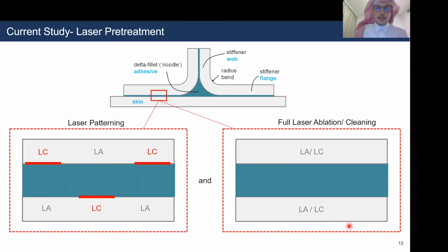So just to illustrate how the laser pretreatment was applied, it was applied to the interface between the flange and the skin. So it is this bottom region here of the flange and the top part of the skin, which are bonded together using the adhesive. And the pretreatment involved, as I said, the laser patterning, which was the alternating pattern between LC and LA, or a full uniform laser ablation or full uniform laser cleaning.